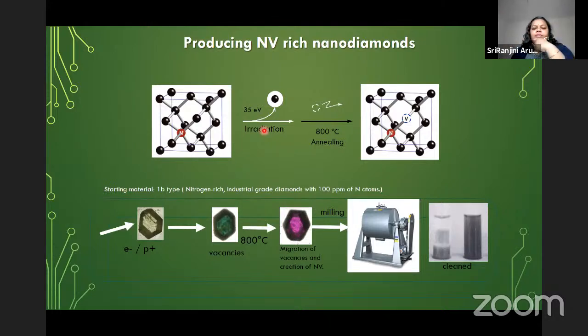And then we anneal at 800 degrees; we have to anneal it slowly. In that case, when the structure is reformed, the nitrogen is retained, the carbon is knocked out, and a vacant site is formed. And these can be characterized by doing a very good TEM or wide field confocal imaging or confocal imaging.